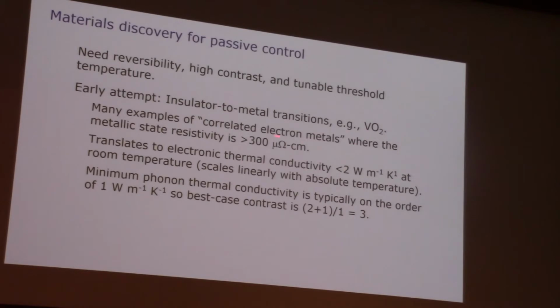So there are a lot of these kinds of systems. They transition between an insulator and what I would call a correlated electron metal. So they have quite high resistivities in the metallic state. If I apply the Wiedemann-Franz law to that conductivity, I would get 2 watts per meter Kelvin. So that's just taking the Lorentz number, multiplying by temperature, you get that value. So you get a number which is quite small. 2 watts per meter Kelvin is not a very big thermal conductivity.